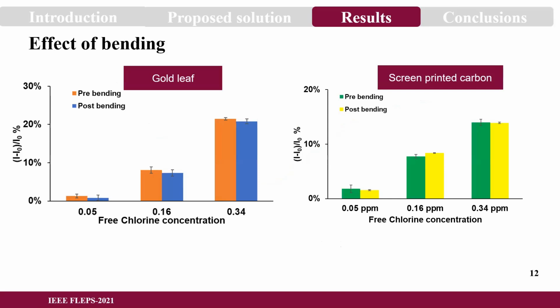Finally, we have shown the impact of bending on these sensors. With gold leaf, all the sensors survived post-bending after 15 cycles to 120 degrees, and the chemical sensing response of the sensors was very similar. While in the case of screen printing, even though the sensing response looks very similar, out of 3 sensors, 1 sensor failed. The major difference you can see is in the current change. The overall current change is less for screen-printed carbon sensors. Even though they are low cost, the sensor performance is lower compared to these gold contact electrodes.